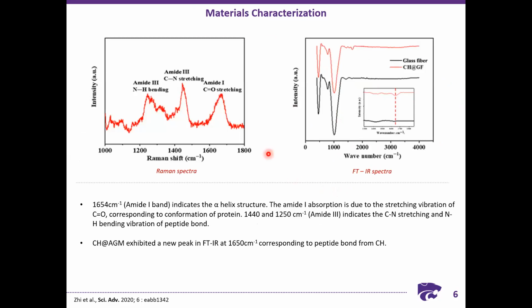Next, in order to confirm whether the peptides from the CH are present on the surface of AGM, they took a Raman spectrum. They found a peak at 1654 per centimeter, which denotes the amide I bond, from the C=O stretching. There are also two other peaks at around 1440 and 1250, which correspond to the CN stretching and the NH bending respectively.